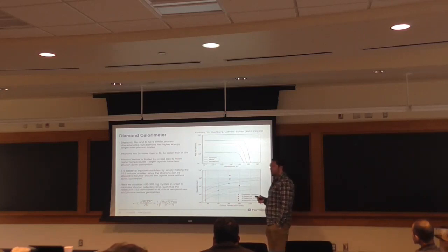So diamond, if you can get really good isotopic purity, which you actually can, the diamond is grown from methane. It's primordial methane that's been sitting underground. All the carbon-14 for the most part is decayed off. People tell me you can't really make stable methane with carbon-13, so it's a high purity source. The upshot of that is the mean-free path is really long. It reaches its maximum at a much higher temperature than either silicon or germanium. So this is probably a more forgiving crystal.